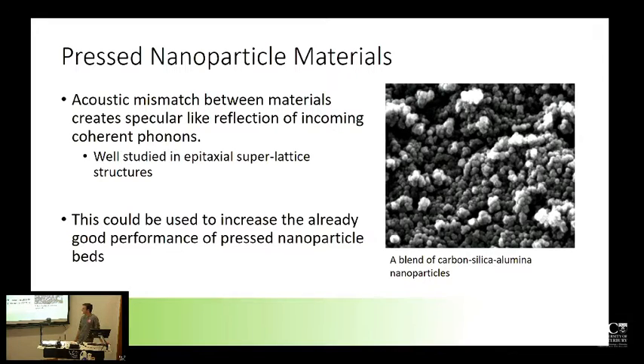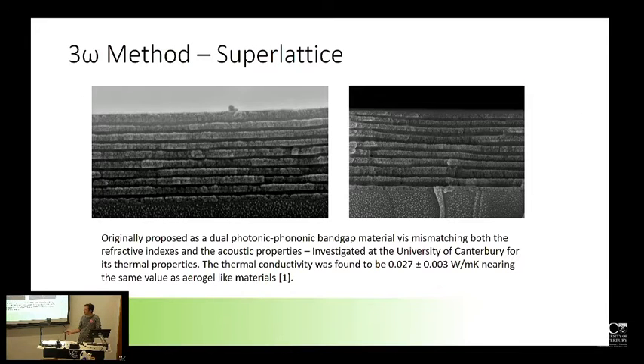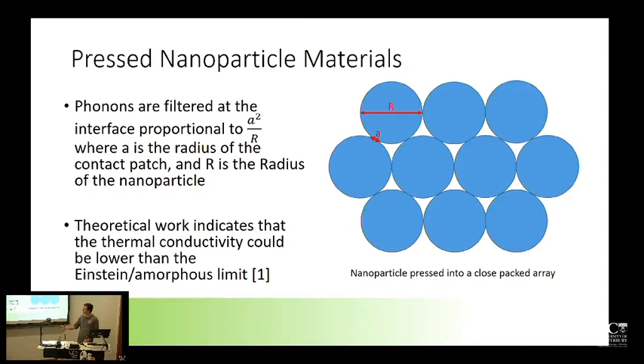So looking further into that, given that people have measured a lot of these nanoparticle beds, what ways could we improve their performance? We were starting to think about something called the acoustic mismatch model. In the same way that when we were looking at the thermal conductivity of the superlattice structure, what if instead of having a homogeneous nanoparticle blend, we started to blend multiple different nanoparticles together into a composite material? So in addition to the radius of constriction reducing the thermal conductivity, we could supplement that effect by also having mismatched mechanical properties between the nanoparticles, possibly increasing the amount of thermal energy that is reflected off these constrictions.